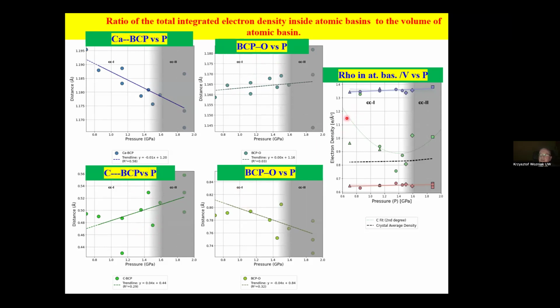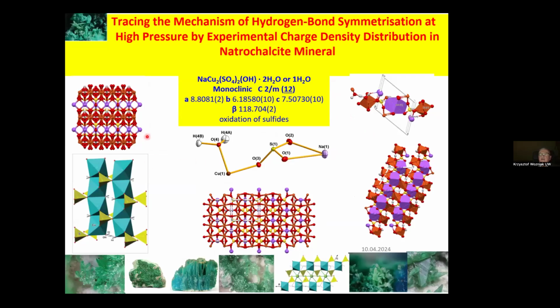And when we divide amount of electron density in given atomic basin by the volume of atomic basin, we see really very nice dependencies for other atoms than for carbon. Carbon is far more sensitive, is changing a lot. And this is why in the other relations we were having big scatters of data points when a carbon atom was involved.